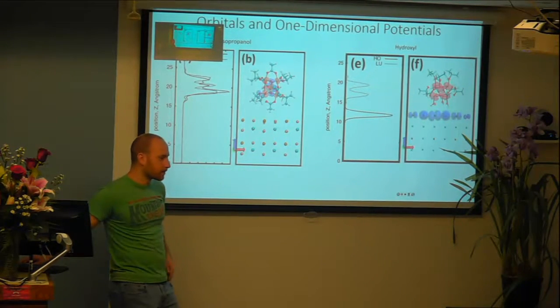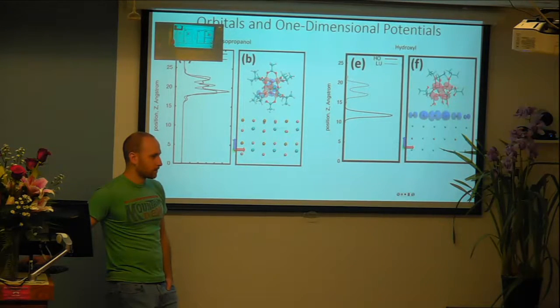Okay. So in the first case, you have both HOMO and LUMO on your nanoparticle, and in the other case, you have one localized on the nanoparticle and the other localized on the surface. And this is what you call a charge transfer. Right. But my understanding is their energy of absorption is very different between these two materials. So you can easily tune the absorption to the range of your perovskite or of your quantum dot, because energetically they're very different, right? So you can imagine that you're really exciting just one system rather than both of them.